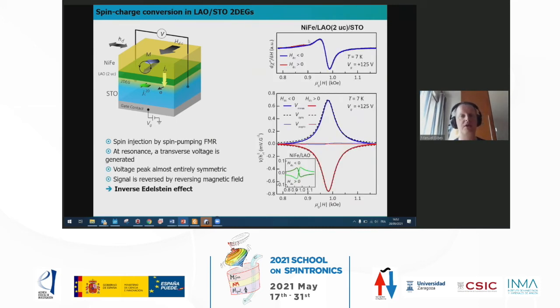So we measure the ferromagnetic resonance. This is a measure of the ferromagnetic resonance signal, if you wish. We see it occurs a little bit below 1 kilo Oersted. And just at the same field, if we measure the voltage, we have two contacts just to measure the voltage, and we see a peak in the voltage appearing just at the resonance. And this peak switches sign when we switch the direction of the magnetic field. Basically, we change the direction of the magnetization, we change the sign. So we really have a conversion from spin to charge, okay? And we can use that to read out the direction of the magnetization in the mesa device. So this is a clear indication of the inverse Edelstein effect.